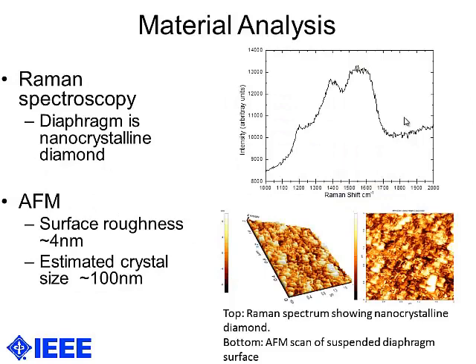We wanted to confirm that this material was nanocrystalline diamond, so we did Raman spectroscopy, and the spectrum, though it doesn't show the strong peak for regular diamond, has been shown to match nanocrystalline diamond under certain deposition parameters. We also ran AFM on the surface of the diaphragm and found that the surface roughness was approximately 4 nanometers and the crystal size was approximately 100 nanometers.